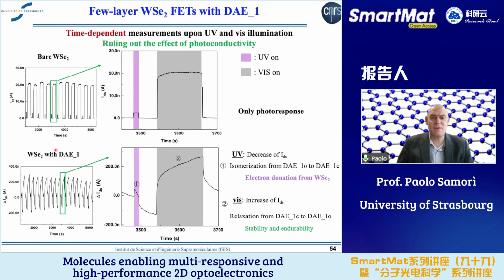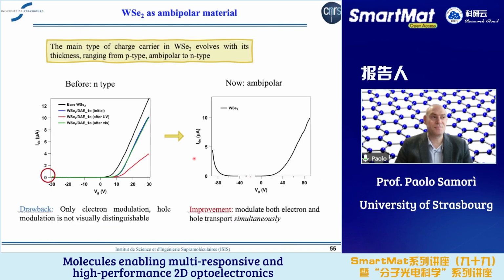Whereas if you do this when you have the diarylethene that is physisorbed on the tungsten diselenide, the UV light is accompanied by a decrease of the current due to the fact that we are creating traps in the channel. And with the visible light, we can actually increase the current through the junction. So the effect of photoconductivity is minor, and the switching of the diarylethene is the important factor for observing the change in the current through a junction.